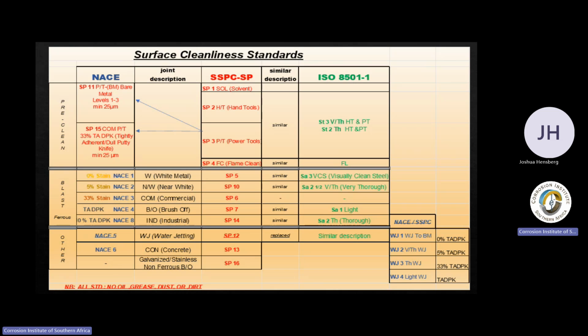So, years ago, Alan Lyle, when he was at Eskom, produced a paper on an exposure survey he'd done on Western power stations. And the results were a big wake-up call for everybody, because the thinner coatings applied to wire brushed steel lasted better than blasted equivalents. The reason was the cover over the peaks. The railways used to use wire brush systems, but multi-coat with MIO primers and that sort of thing. And they last for many, many years. So I just want to emphasize that if you haven't got enough cover over your peaks, watch out.